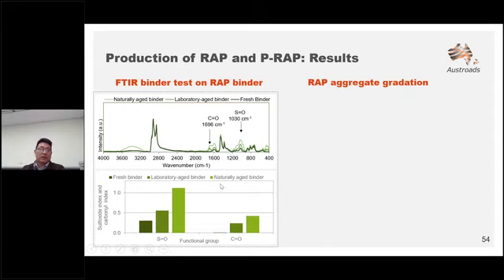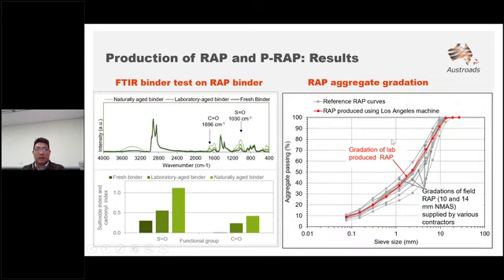We should note that the lab aging protocol chosen in this study was aimed to simulate 10 years of aging in the field. So for the RAP gradation, we collected the gradations of field RAP with the nominal aggregate size of 10 and 14 mm from contractors across Australia and New Zealand, and used them as the references. As you can see here, the grey curves, and the red curve is the gradation of RAP produced in the RMIT lab. So the RAP curve falls within the range of the reference curves. So for that, this RAP gradation was used for the further steps.